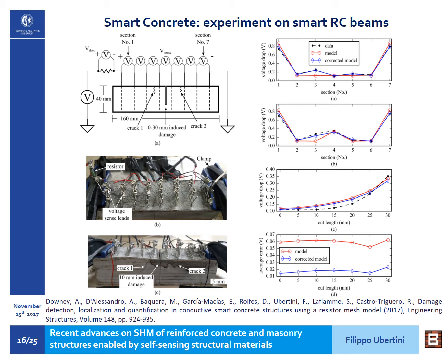And here, for example, I show you the application to a small beam, where we give this square wave voltage input across 2 electrodes, and we measure voltage drops across all pairs of electrodes. We see that voltage drops are larger in correspondence with external electrodes, that are those that carry the electrical contact due to a local contact resistance, and they are of the same order of magnitude for the remaining pairs of electrodes.